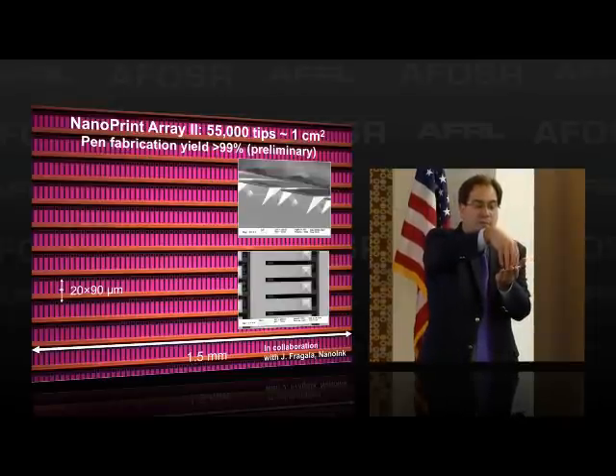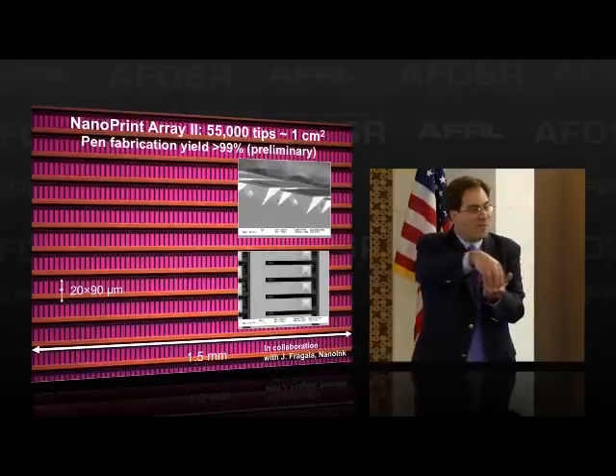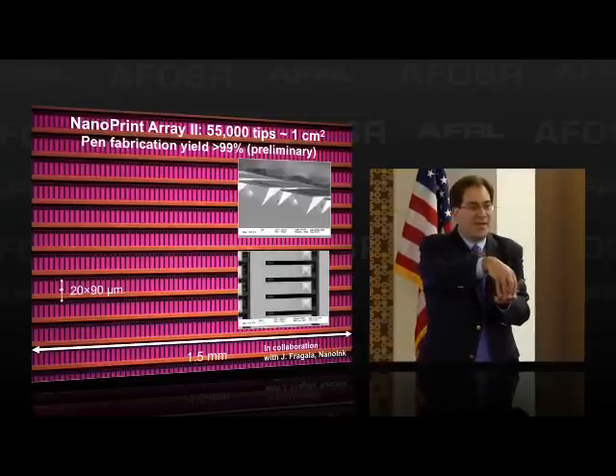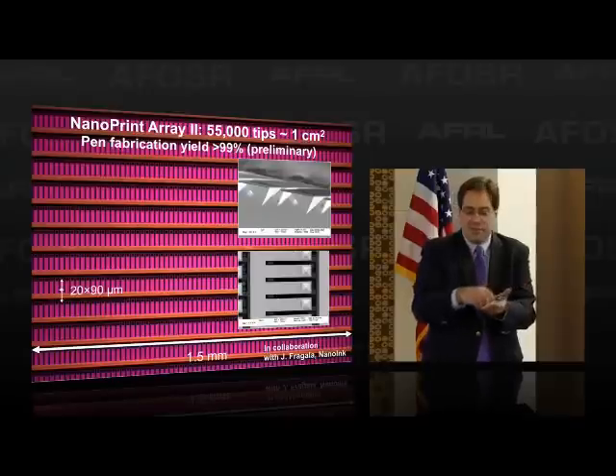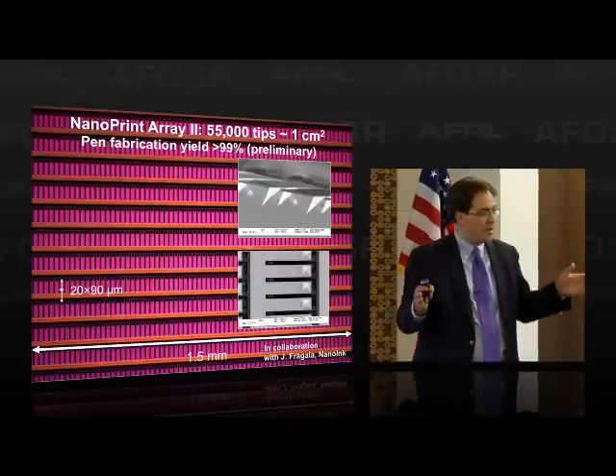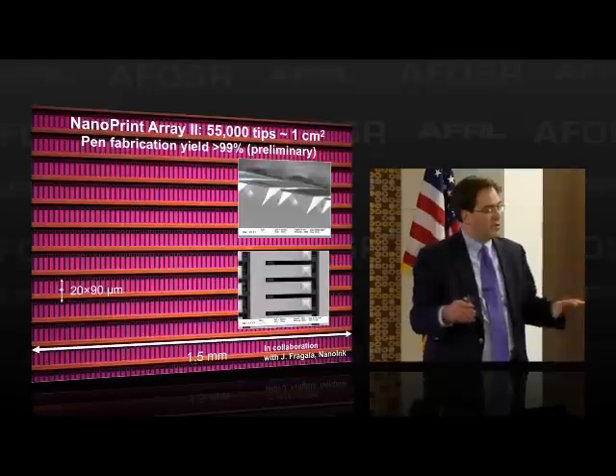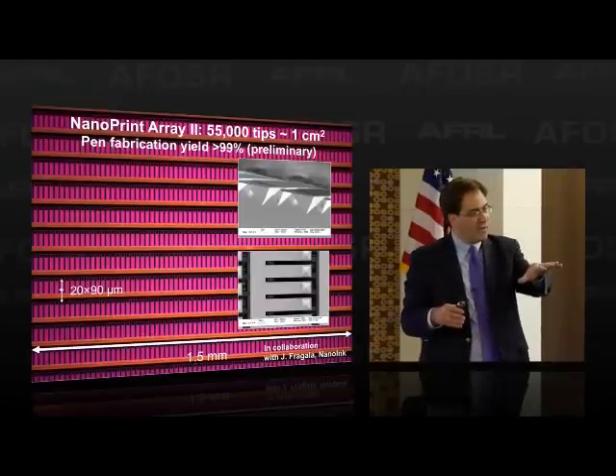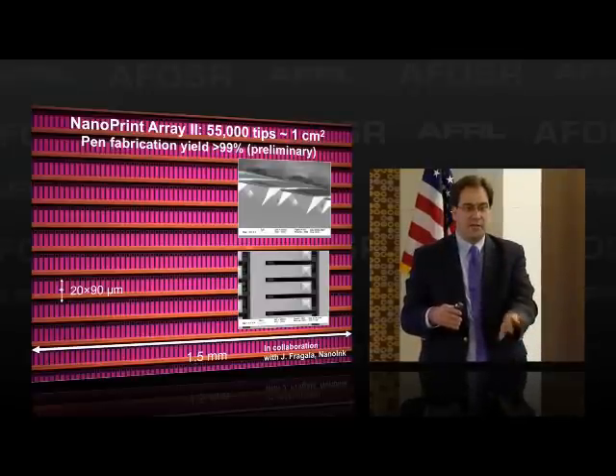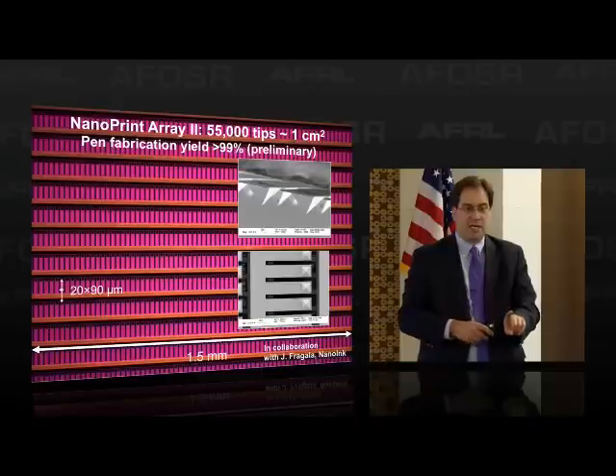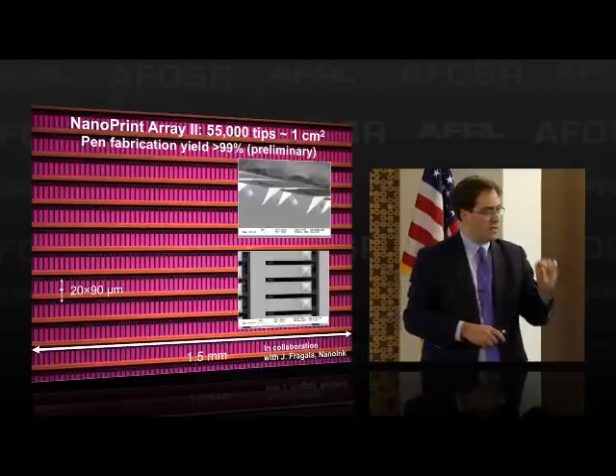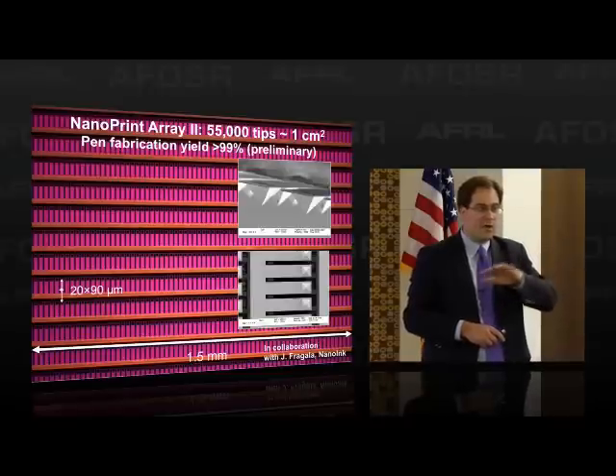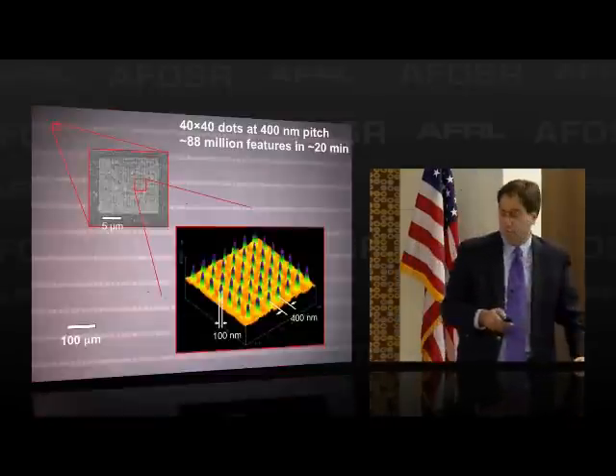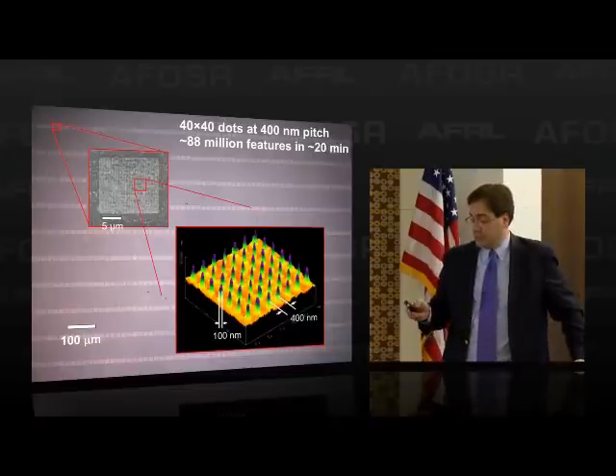And so if I push and get them all in contact, if I'm delivering energy to the surface, the problem is I have a different contact force at each point of contact. But with this type of experiment, in terms of the DiP-Pen transfer of molecules, it doesn't matter. So what I can do is effectively use gravity and bring all the tips in contact. If the shortest tip is in contact, then I know all the other tips are in contact. So we actually intentionally put in tips that are a little further away, so that if that one is in contact, we've got all the other tips in contact. And in principle, we should then be patterning molecules over, in this case, square centimeter areas.